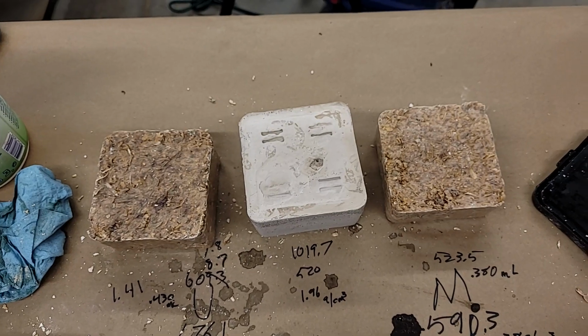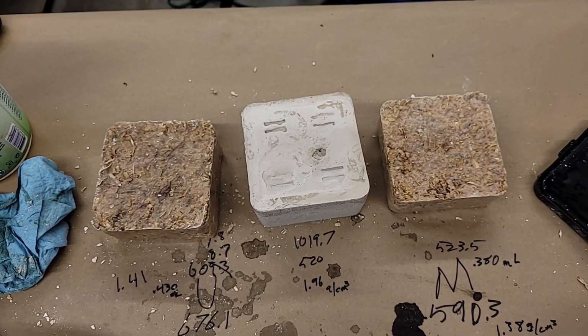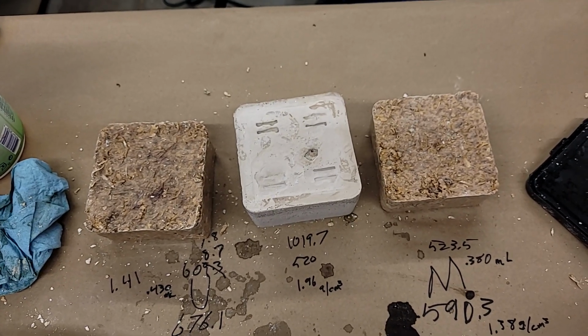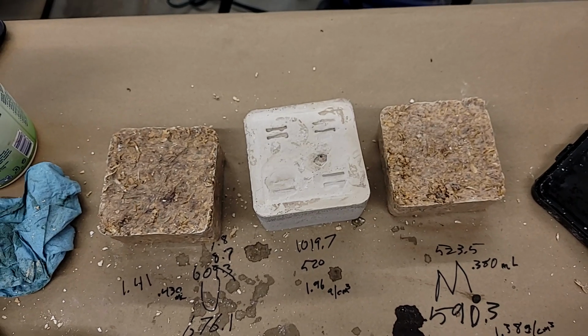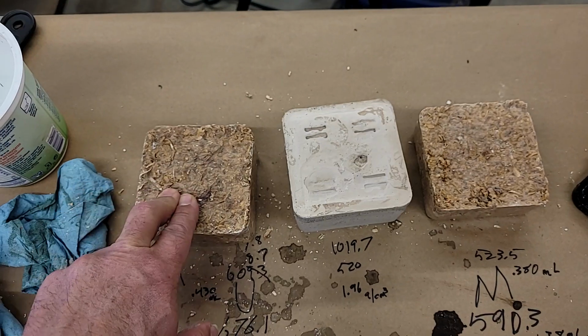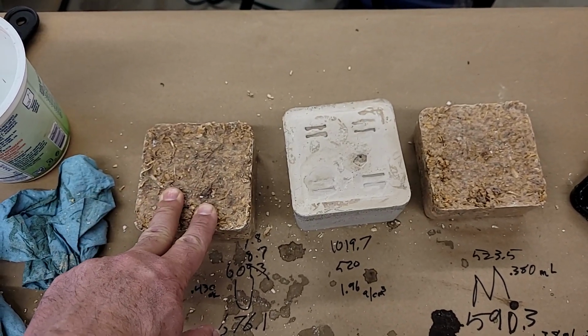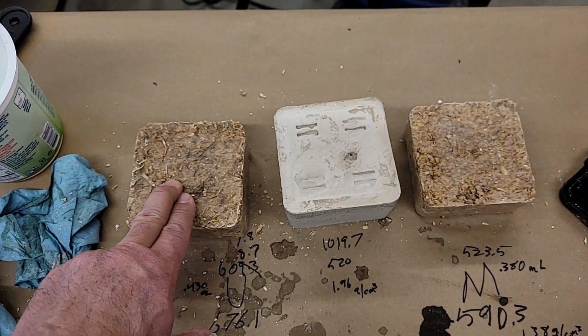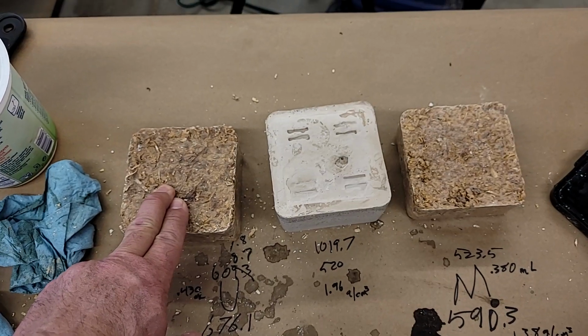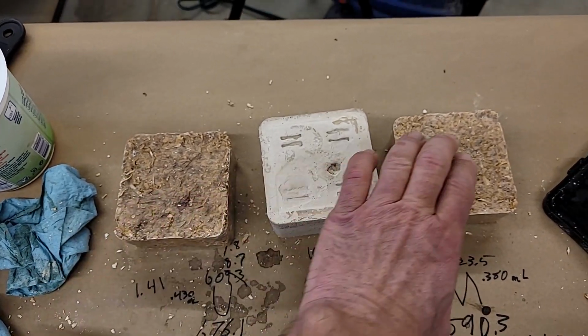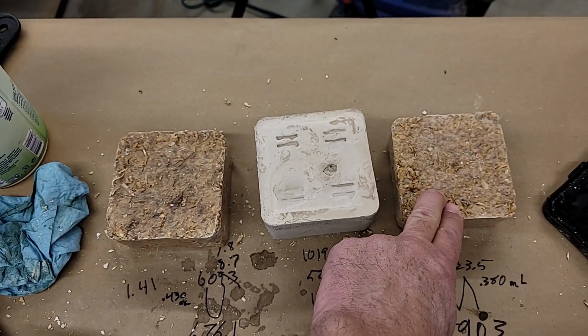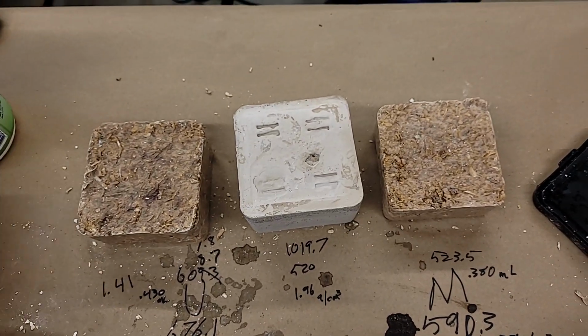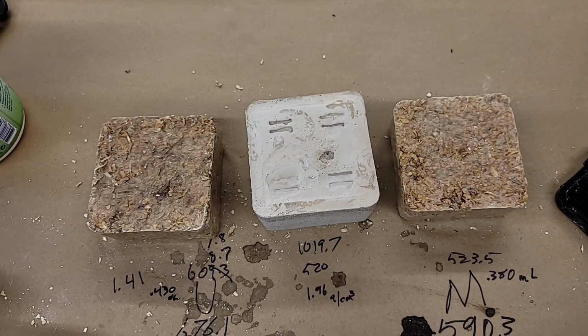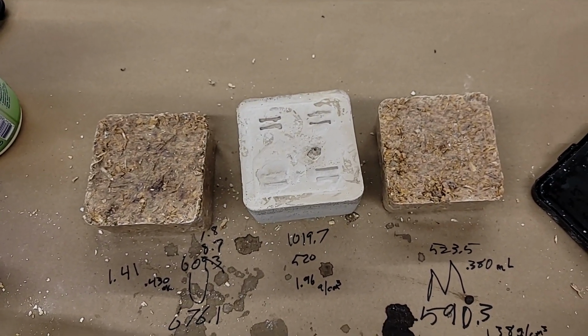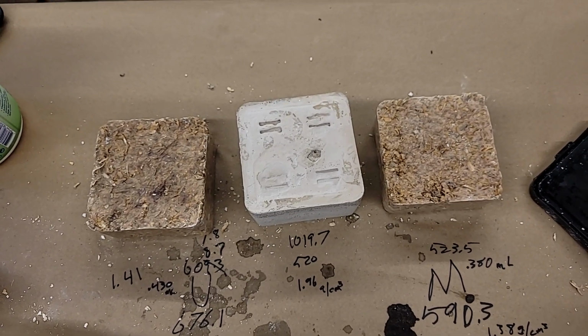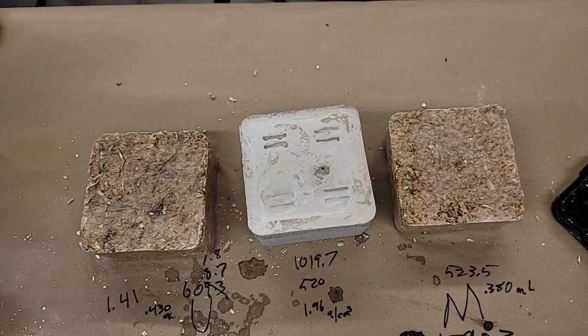for about 24 hours. What I noticed yesterday when I checked them about 2 hours after the initial molding process is that the unmodified version actually was setting up faster. So it was hard about, I guess, 2 to 3 hours after. I don't remember exactly when I checked. And then the modified sample was still a little soft. It had a little bit of give to it. I don't know if that's because the unmodified sample simply extracted more moisture out of the system, which then caused a more rapid reaction. I'm not sure what the reason was for that.